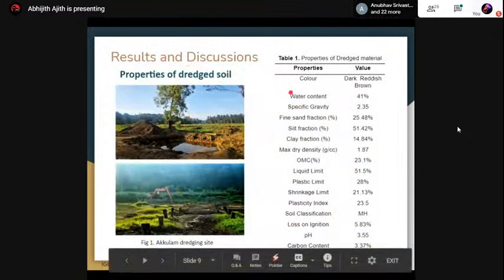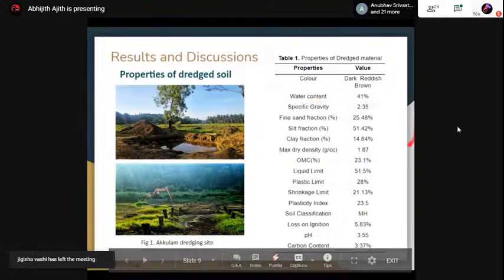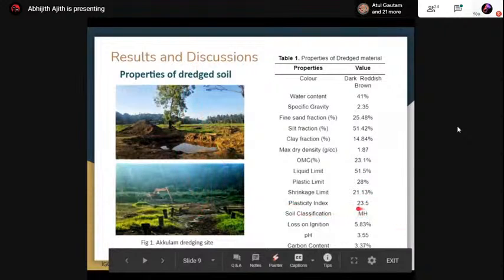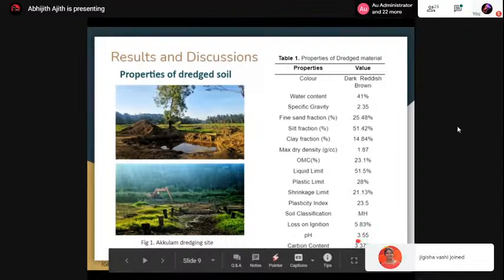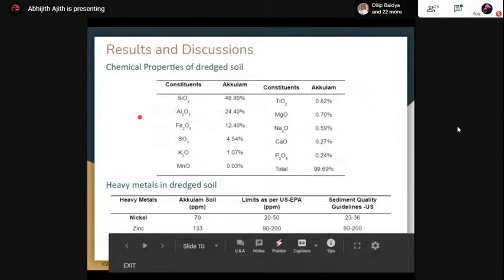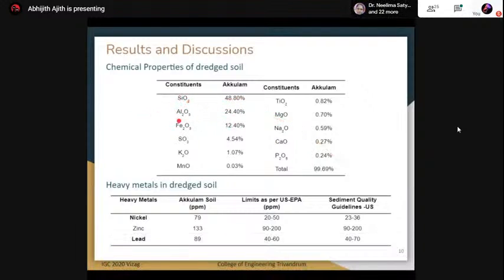Now, moving on to the results, the geotechnical properties of the dredged material are listed here, and here is the Akkulam dredged site. The soil has been classified as highly compressible silt as per the IS classification, and the pH is about 3.55, which is really acidic. Looking at the chemical constituents, the major content is silica, alumina is about 25%, and there is a considerable amount of ferric iron as well. But when you look at the heavy metal contamination, as per the US EPA standard and sediment guidelines by the US, we can see the soil is heavily contaminated with nickel and lead, whereas it is moderately contaminated by zinc.